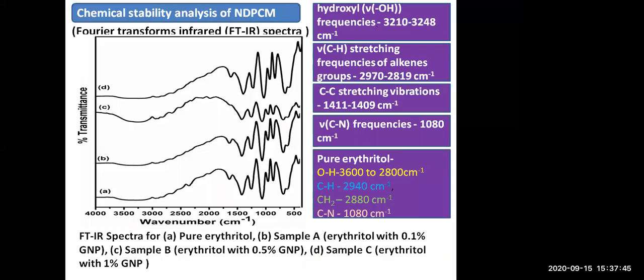Then chemical stability analysis of the NDPCM. The Fourier transform infrared, that's FTIR, spectra was measured in a range varying from 4000 centimeter per -1 to 400 centimeter per -1. This observed FTIR result suggests that there is no chemical reaction between erythritol and graphene, as the change in all peaks between pure erythritol and graphene erythritol is negligible.